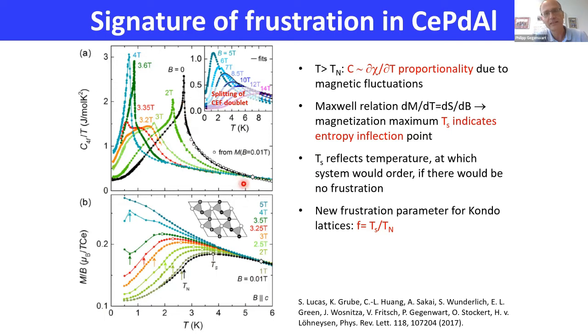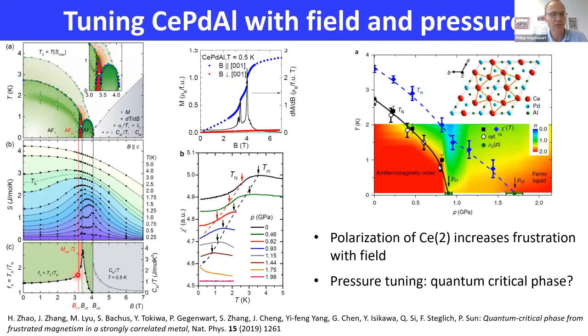And so our idea is that the system, if it weren't geometrically frustrated, would form the ordered state at this entropy inflection point, so that Ts would be the true magnetic ordering temperature if it weren't frustrated. And so we can define a new frustration parameter, which is just the ratio of this expected ordering temperature divided by the actual ordering temperature. If we now apply magnetic fields and follow this frustration parameter, we see that it grows enormously as we enter the series of different antiferromagnetic states by field in this material. Furthermore, we can also follow the evolution with pressure of this entropy accumulation point, and that's shown here out of that study. And we see that